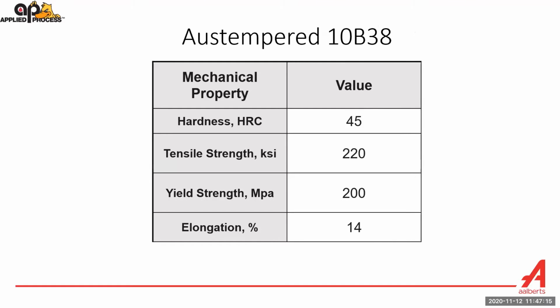Recently, we did a test on 10B38, which is about the lowest carbon and alloy steel that we can effectively Austemper. We Austempered the part to 45 Rockwell C, and we had some amazing mechanical properties. And I just noticed an error on my table here. The tensile strength in KSI was 220. The yield strength in KSI, not megapascals, is 200 KSI. And it had 14% elongation before it failed. So the area under the tensile curve was dramatic, which relates to the energy that the part can absorb.